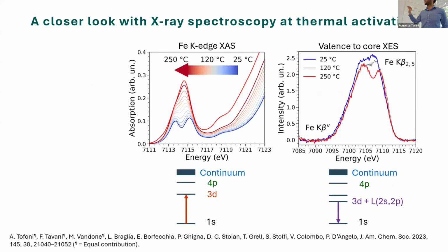Well, what is happening at the local level? Wow, many changes. So let me disentangle this. Here I am displaying the iron K-edge XAS spectra as a function of time and temperature. We go from the blue curve, which is the spectrum of the pristine MOF, the resting state, while we are heating, and the curves are becoming redder and redder.